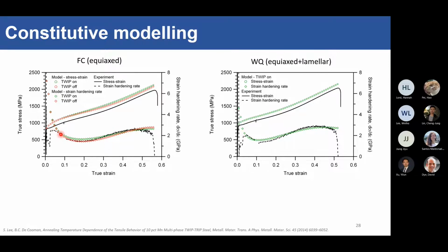So it overshoots a little bit, and that's because the model doesn't quite take into account this slight yield point elongation here. And also we've got good agreement with the rest of the strain hardening curve for both the FC and the water quench sample. And now because we know this is simultaneous TWIP plus TRIP, that means in the model we can actually separate the twinning contribution and the TRIP contribution. So the contribution to strength from the TWIP and the TRIP effect. And we can plot them on the graph here.